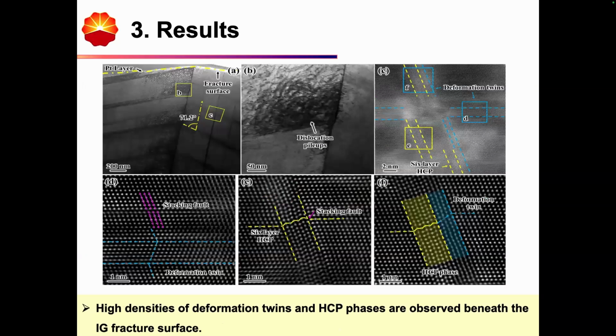Then we extracted the microstructures just beneath the intergranular fracture surface. We can see also some very complicated substructures. First is the deformation twins contoured with green boundaries, which causes some extensive dislocation pile-ups.